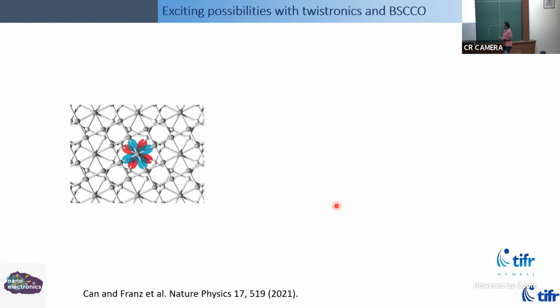So we got into this based on a lot of activity in the community after a theory paper came out, which basically said if you have two layers of a high temperature superconductor like BSCCO and you rotate them by 45 degrees and put them on top of each other like this, so you have an order parameter of the upper layer which is blue and the order parameter of the lower layer which is red, then if you just look at the geometry, there will be no supercurrent through this system because the nodes are overlapping with the antinodes.